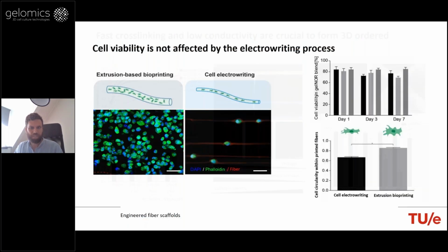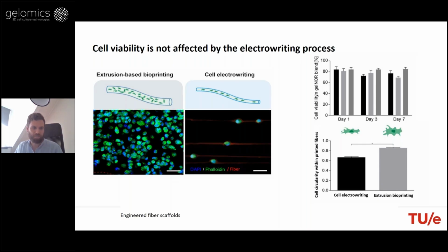The next step was to incorporate the cells and then look at cell viability. What you see here is a comparison between extrusion-based printing with cells encapsulated and our cell electrowriting process. In this cell electrowriting process, you create filaments with isolated cells, forming a necklace-like type of filament, somehow aligned, but this alignment still has to be further evaluated, while in the extruded printed filaments you see a heterogeneous distribution of cells with no preferential organization, of course with a higher cell density.